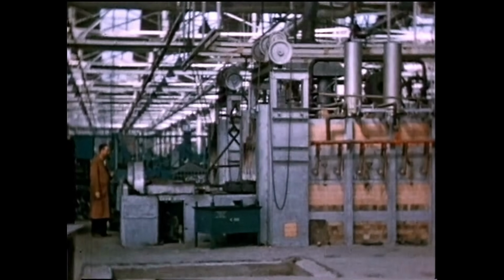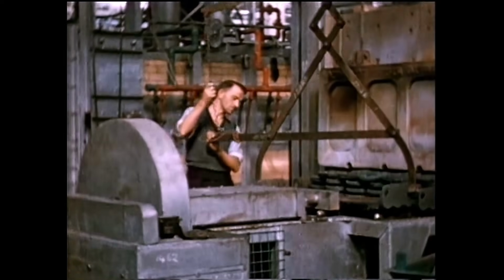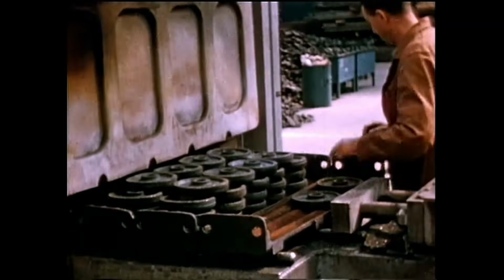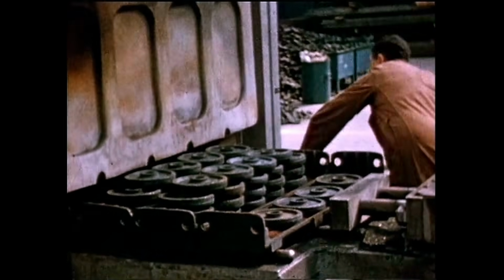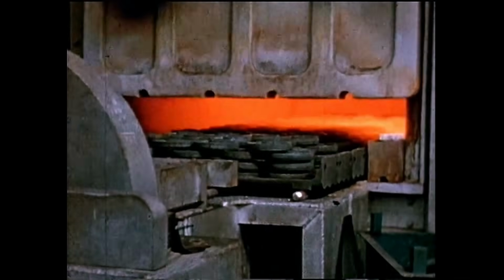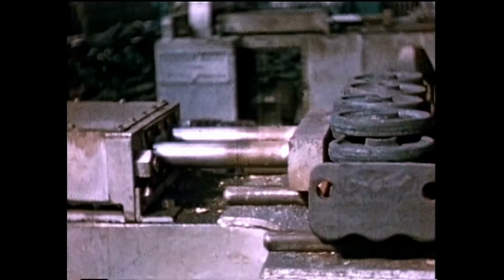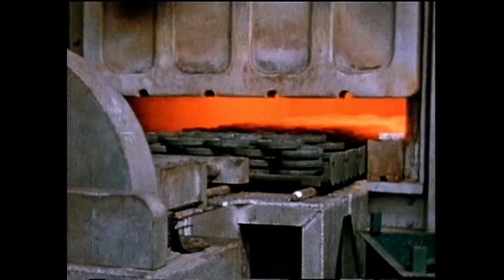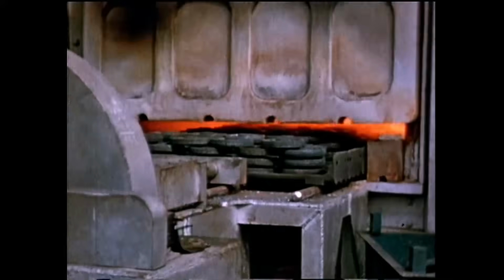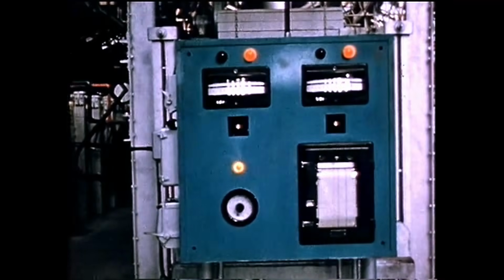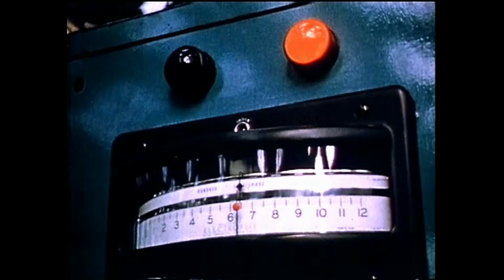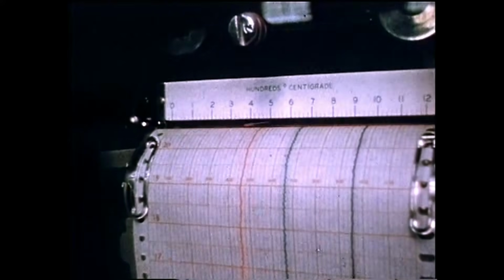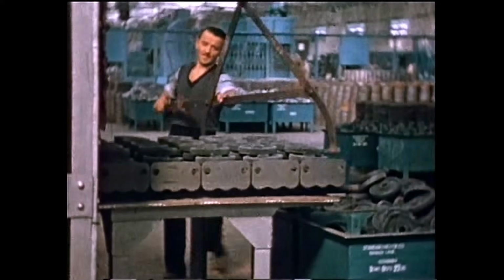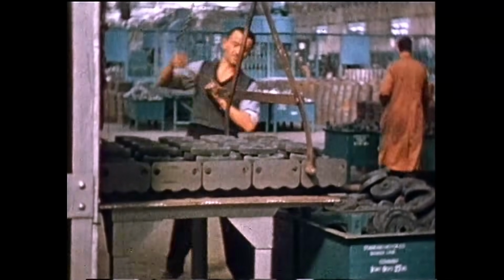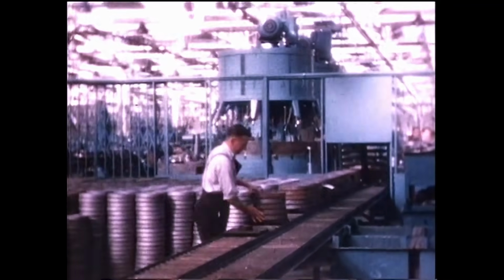Here is one of the 5 continuous annealing furnaces which are installed in the stores department. The stampings to be treated are loaded into special trays, each of which accommodates 170 pounds of work. It takes 10 hours for the work to pass completely through the furnace, during which it attains a maximum annealing temperature of 950 degrees centigrade. Baffles inside the furnace control the rate of cooling. After annealing, the stampings pass on gravity roller conveyors to the machine lines.